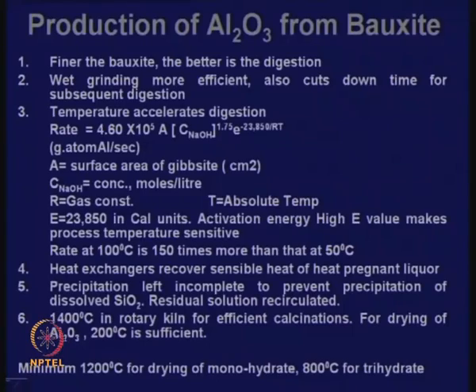So, there are companies which operate at much lower temperatures, almost without autoclaves. They would rather go for very fine bauxite, grind it much finer, use stronger alkali, etcetera. So, this is an example of why one company and another may not do the same thing. In India, there are 4 or 5 aluminum companies. They do not have the same conditions for Bayer's process. They have different conditions. But basically, these are the parameters.